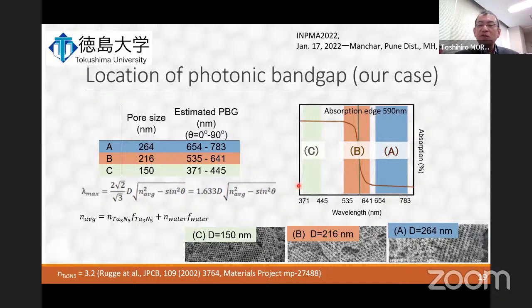So we could calculate the estimated photonic band gap for the sample with the largest pore A, medium B, and smallest pore C, which are tabulated here. For sample A, the photonic band gap would exist in the pale blue region, this region. B, this is the red region, and C, the pale green region, okay?